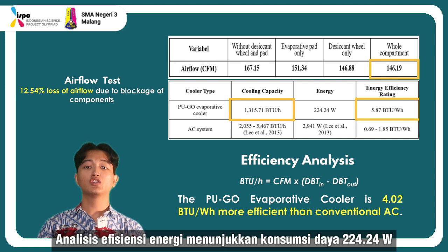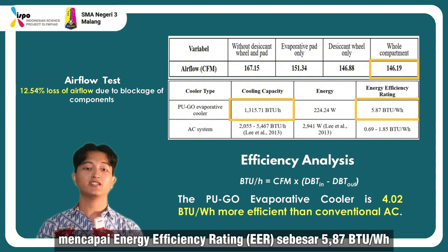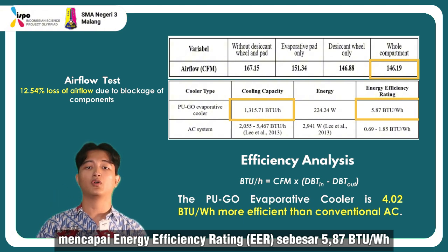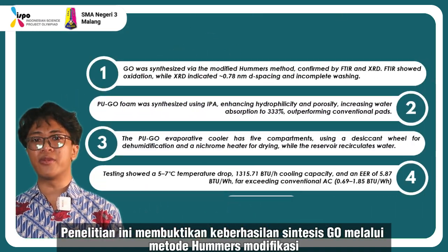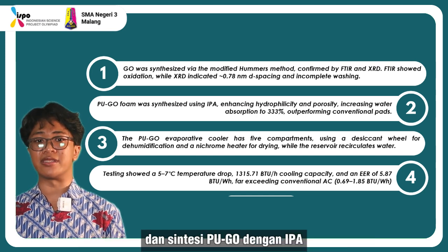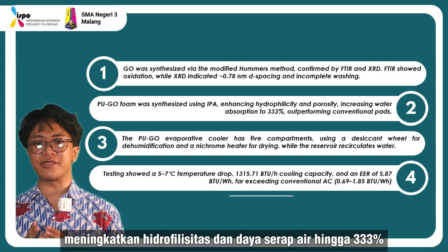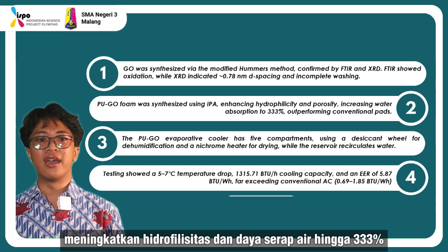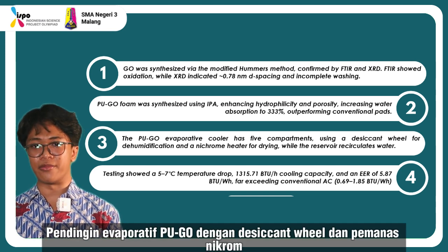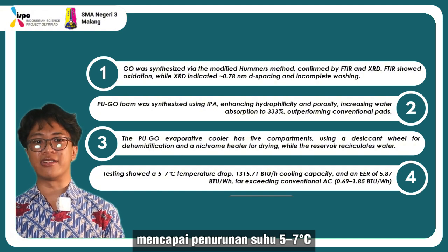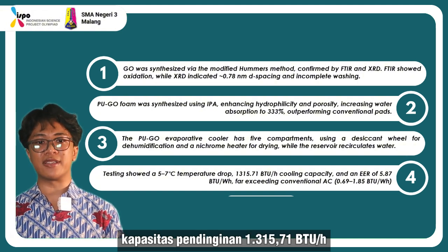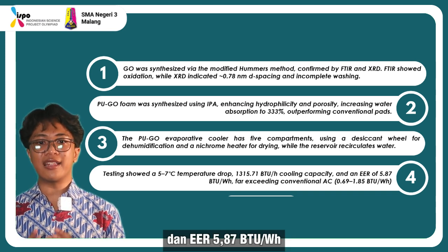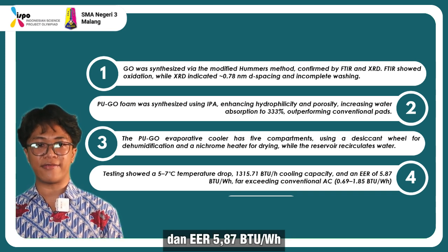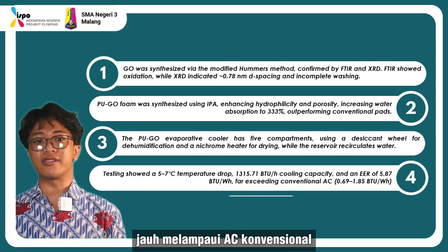Energy efficiency analysis showed 224.24 watts power consumption, achieving an energy efficiency rating of 5.87 BTU per watt hour, far exceeding conventional AC. Our research confirms successful GO synthesis through modified Hummers' method and PUGO synthesis using IPA, enhancing hydrophilicity and water absorption to 333%. The PUGO evaporative cooler with a desiccant wheel and nichrome heater achieved a 5 to 7 degrees Celsius temperature drop, 1,315.71 BTU per hour cooling capacity, and energy efficiency rating of 5.87 BTU per watt hour, far surpassing conventional AC.